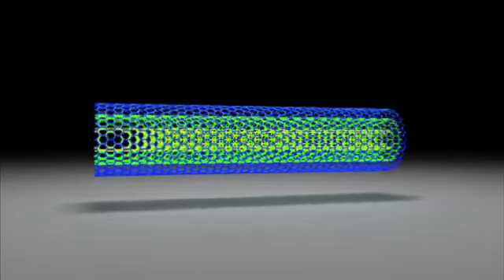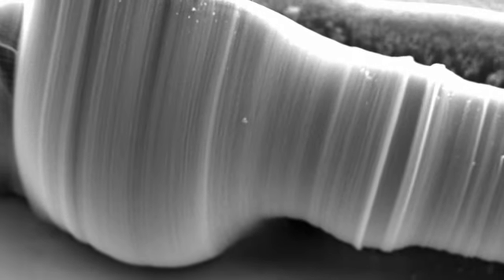The Goddard samples were grown multi-walled, so they're not just single-walled nanotubes, and they're also oriented straight up and down. The reason that the oriented samples are darker is because they're low density, light can go in, it gets rattled around in there and it gets absorbed. Over a long period of time after all these experiments, we discovered that alumina is really the trick to getting the nanotubes to stick. So now you have to scratch them off.